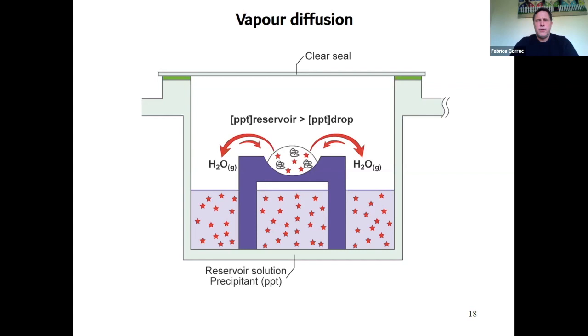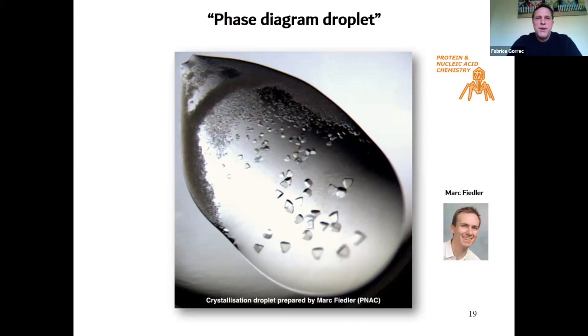So because the drop has less precipitant than the reservoir, you have a dehydration of the drop by osmolarity. So that's how the concentration of the protein in the drop rises. So here it's an interesting case, which I call the phase diagram droplets. So you're in this vapor diffusion droplets set up by Mark. You can see the different phases, precipitation, nucleation, microcrystals, and relatively larger crystals. So in this case, you can be almost sure that it's protein crystals even before you shoot them.